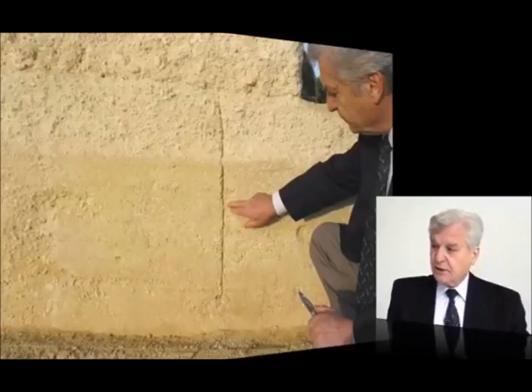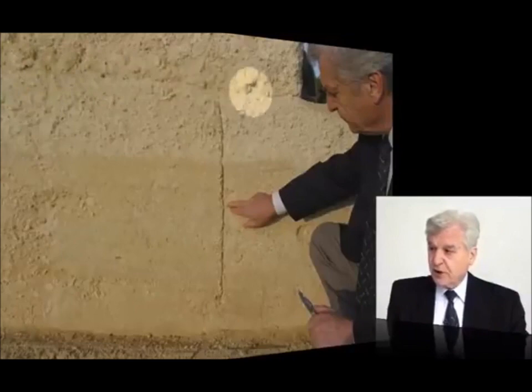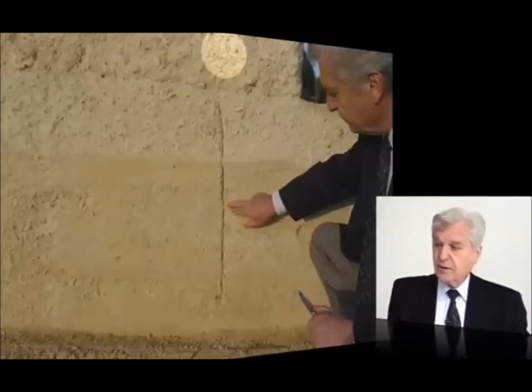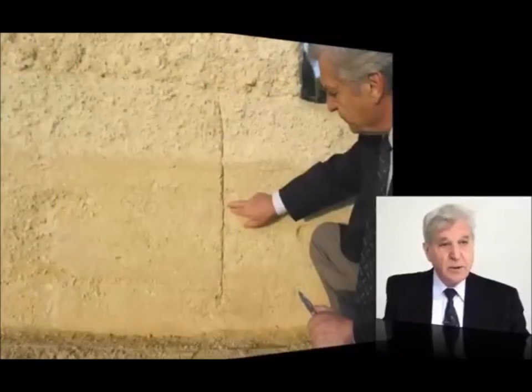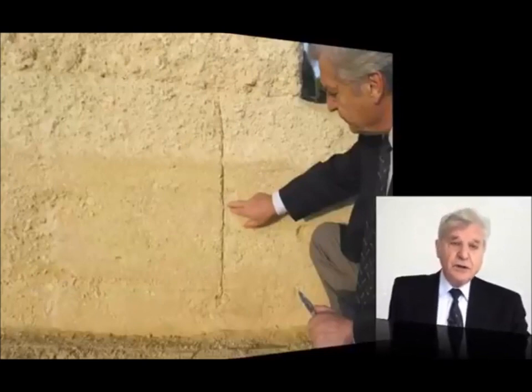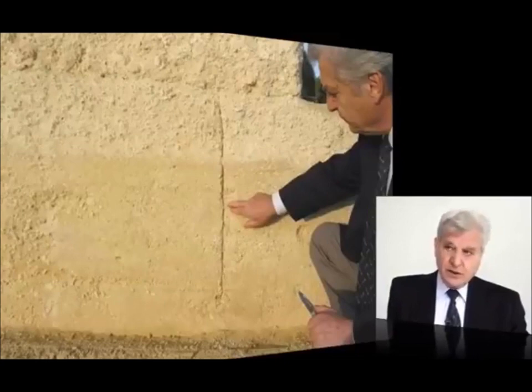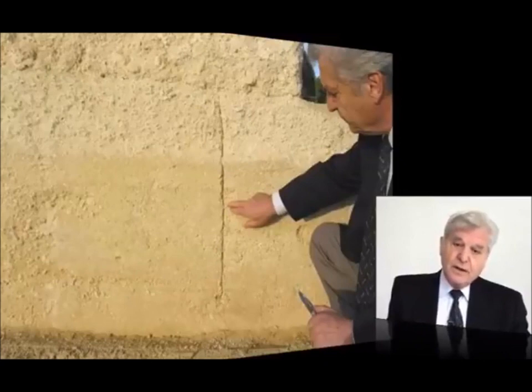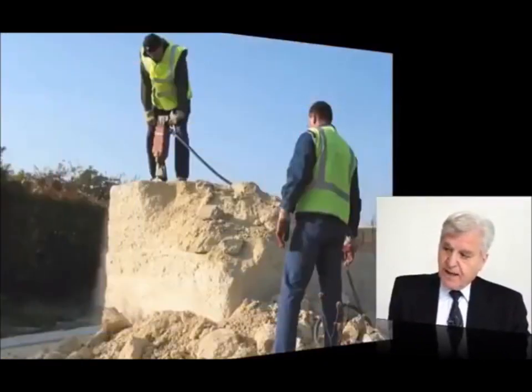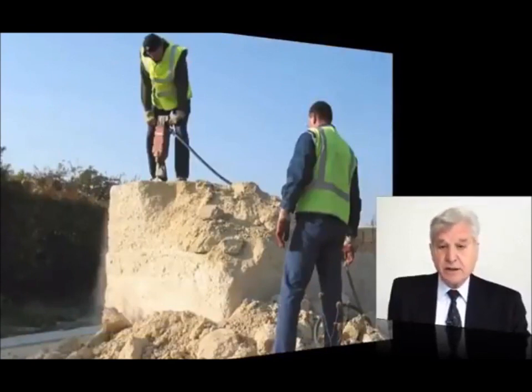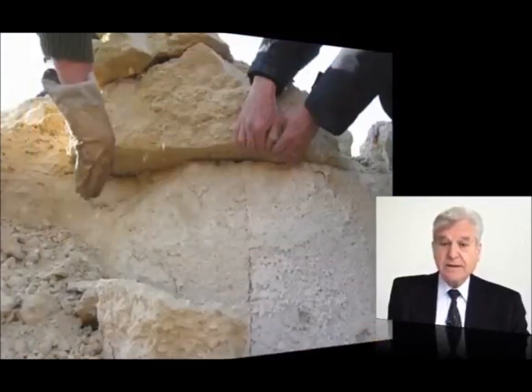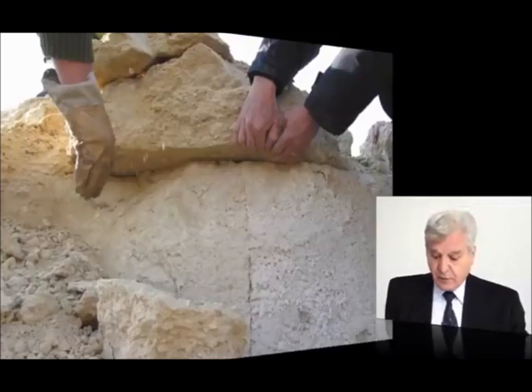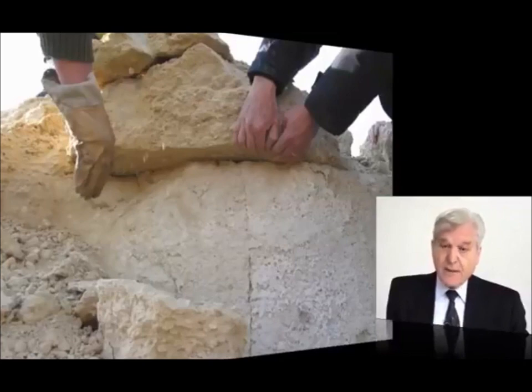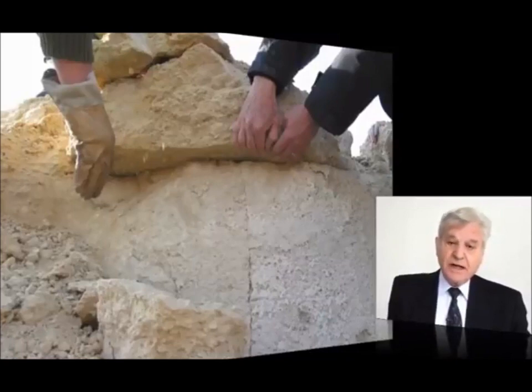But above it, you see that the stone above the 2 others, we don't see practically any joint, and we feared that the blocks would be glued together. This is what people are always telling us: if you do this type of experiment, your stones will glue to each other. We had to destroy what we had manufactured, and during the crushing we were capable of separating very easily the upper block from those at the bottom, and we saw that they were absolutely not adhering to each other, but that in fact the surface of each block was exactly fitting with the surface of the other one.